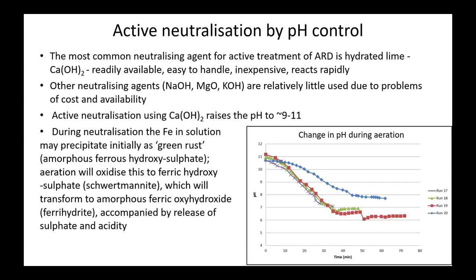You add it to the acid mine drainage, and the first thing that happens is you precipitate the iron. And initially, it often precipitates as Fe2+. The iron is released by breakdown of pyrite, and it's released as Fe2+. If that precipitates quickly as ferrous hydroxide or ferrous hydroxide sulfate, that's what's often called green rust, which is a dark green precipitate. If you oxidize that by aeration or just letting it sit in oxygenated water, the Fe2+ will turn to Fe3+, and it'll turn from green to orange.